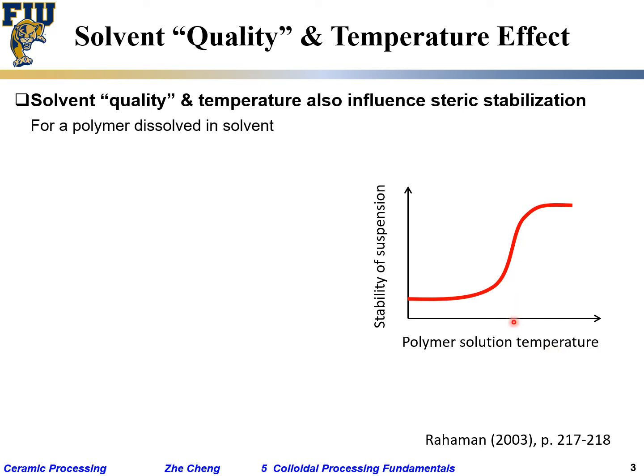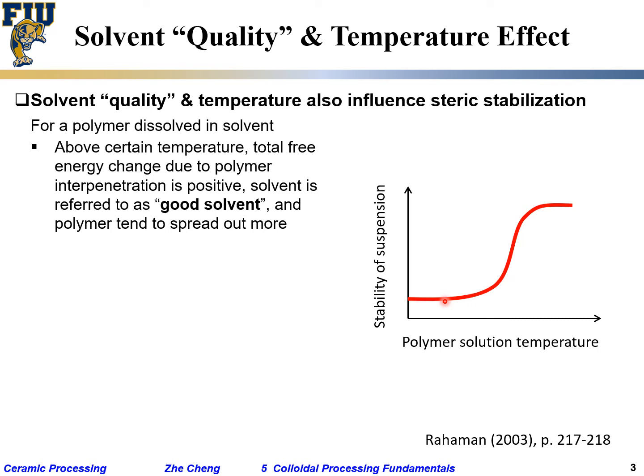And what people find is above a certain temperature, the suspension appears to be more stable, while below a certain temperature, the suspension is less stable. So what people believe happens is, above the certain temperature that we roughly show here, the free energy change due to the polymer interpenetration is positive, which means the polymers do not really want to interpenetrate each other. And the solvent in this case is referred to as a so-called good solvent.